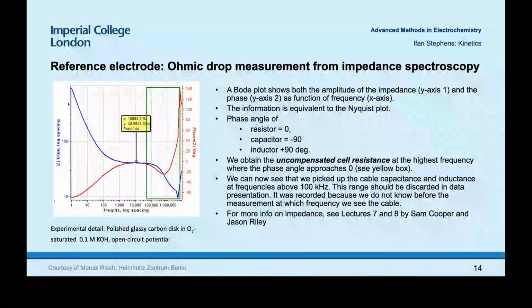So you see the total amplitude of the impedance is the blue, and in red you've got the phase. So recall that the phase angle of a resistor is 0 degrees, a capacitor is minus 90 degrees, and an inductor is plus 90 degrees. So what we can see is we can obtain the uncompensated cell resistance at the highest frequency. So the frequency is going up here. So the highest frequency where the phase angle approaches 0. So that would be here. And at frequencies above that, above 100 kilohertz, we can see that we actually picked up the cable capacitance and inductance. So this is actually irrelevant to the electrochemical data. So if you were talking specifically about the electrochemical data, I wouldn't even plot this part here because it's not relevant. For more info on impedance, see lectures 7 and 8 by Sam Cooper and Jason Riley.